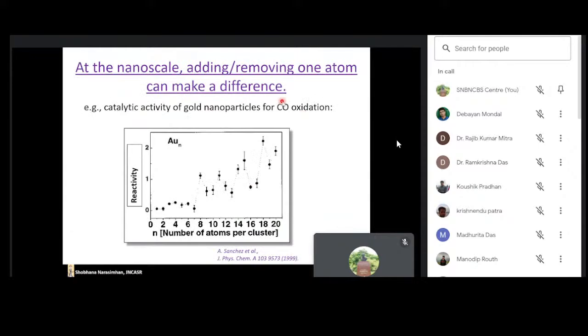And in my title, I said one atom at a time. So why did I say that? Because at the nanoscale, adding or removing one atom can make a difference. So this is, for example, the catalytic activity of gold nanoparticles for CO oxidation. On this axis is the reactivity. Here is the number of atoms in the particle. And you notice that, for example, if you have 8 atoms in your gold nanoparticle, it's a pretty good catalyst. But if you have 7 atoms, it's a lousy catalyst. And if you have 9, also it's not so good. So every single atom makes a difference.